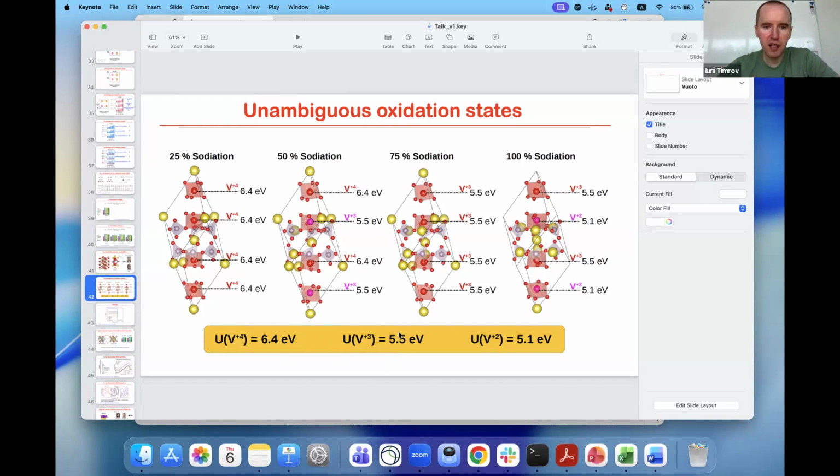When you decrease oxidation state, you are adding more electrons to your vanadium, right? So you have more and more electrons in vanadium. And those electrons increase the electronic screening of the Coulomb interaction. As a consequence, this Hubbard U goes down. I think that could be one interpretation. So when oxidation state decreases, Hubbard U decreases. It's a good question.